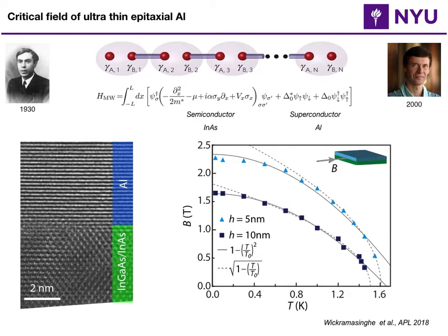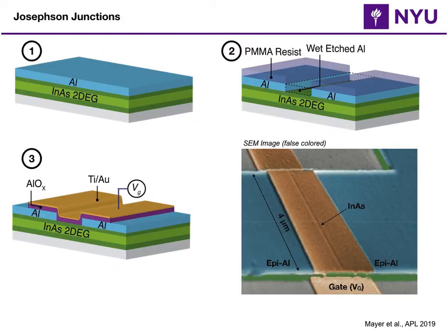If we assume the indium arsenide band parameters, the crossing happens around half a Tesla. That's where g mu B is almost the superconducting gap. And so both of these values are above half a Tesla and quite good for this purpose. So we pursue the Josephson junction route to realize these Majorana fermions.